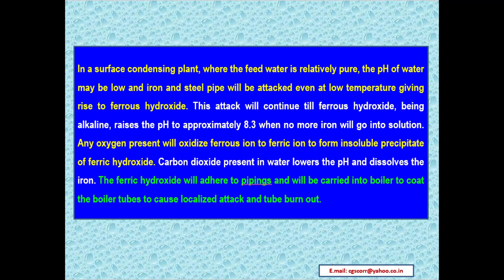Any oxygen present will oxidize ferrous ion to ferric ion to form an insoluble precipitate of ferric hydroxide. Carbon dioxide present in water lowers the pH and dissolves the iron. The ferric hydroxide will adhere to pipings and will be carried into the boiler to coat the boiler tubes to cause localized attack and tube burnout.